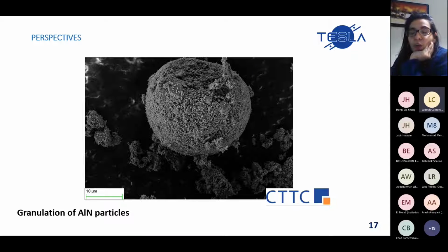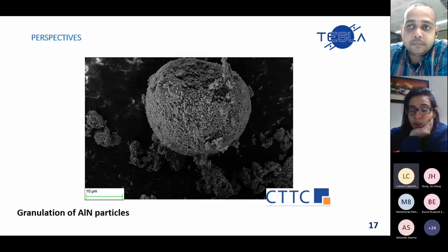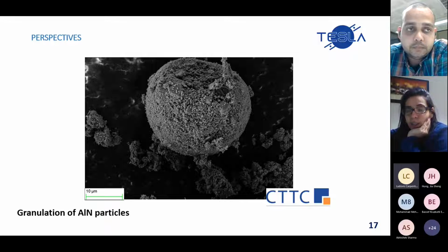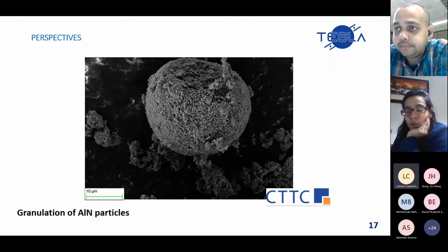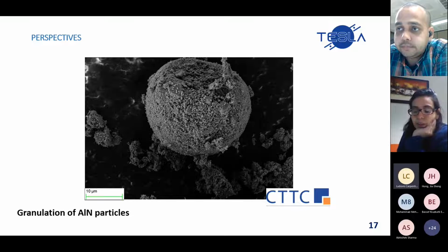For the dielectric properties, the loss, you require the highest density possible and the lowest porosity inside, because of the porosity and also the impurities. At ppm levels, the higher the frequency you go, the lower the impurities you need to have inside the crystal of the material.